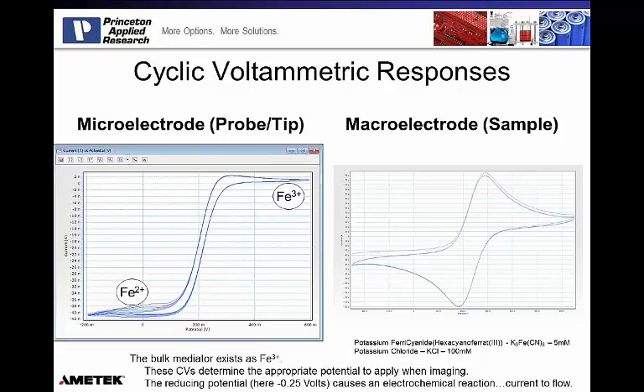So here we have the cell comprised of a 5mm gold disc. We're working with a probe that is a 25 micron platinum probe with an RG ratio of 10. Then as a supporting electrolyte, we have 100 millimolar KCl. So in the image on the left, we have a typical sigmoid shape of a response of an ultramicroelectrode in a cyclic voltammetry experiment. When I created the solution, my bulk ion exists as iron 3+. And so that's important to know, because if I look at the oxidizing potentials, the positive potentials on the right, iron 3 plus exists, and there's basically no electrochemistry happening at the positive potentials because I'm already starting with iron 3 plus in the bulk state.